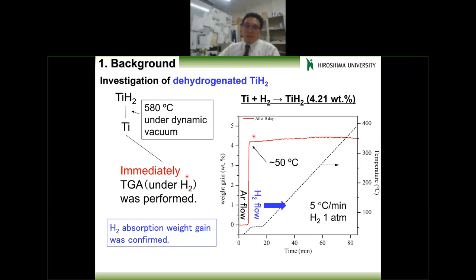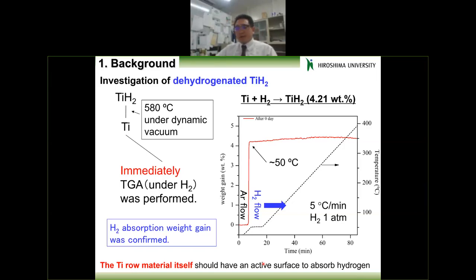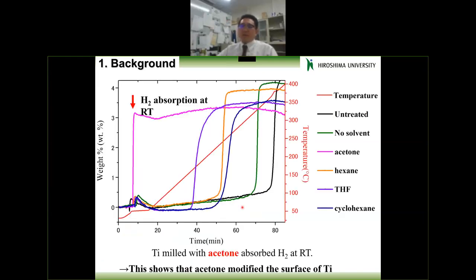So that is quite drastic, but that immediacy is quite important. It means this titanium raw material itself should have a quite active surface to absorb hydrogen. But if we expose it to air, or even in a glove box, titanium immediately oxidizes. That means some stable surface is generated, and that blocks hydrogen absorption. So that is the reason why titanium shows quite bad kinetics for hydrogen absorption. But if we perform hydrogen desorption and then immediately try hydrogen absorption, in this case titanium itself shows quite active behavior to absorb hydrogen at room temperature. But unfortunately, this cannot be kept for a long time because it is too active to keep that active state, since it is immediately oxidized.